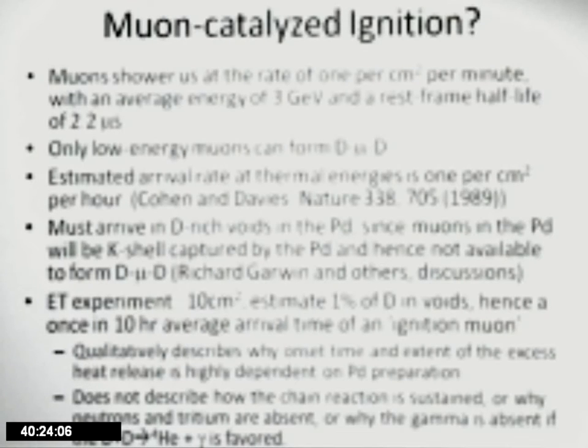And again, it has to be in the D-rich void. Since it gets anywhere close to the Pd, it will be muon K-shell captured, essentially 10 to the minus 12 meters from the nucleus, and trapped by the palladium and never available to form this d-mu-d muonated molecule that would then fuse.